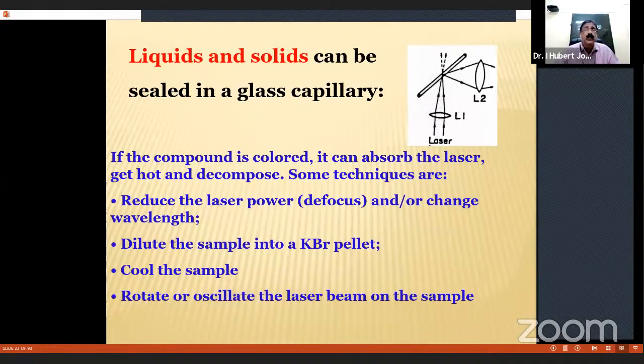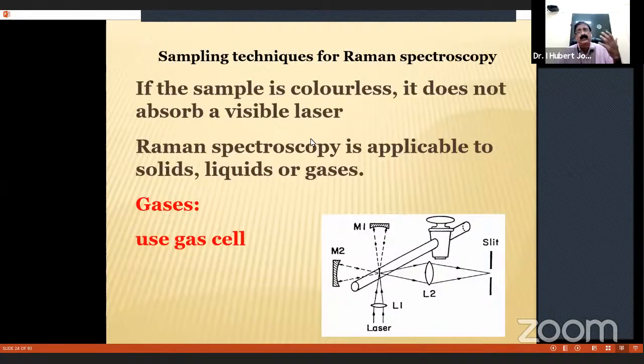In the case of a liquid sample or gas, or solids such as powder, the molecular sample can be sealed in a glass tube. Suppose the sample is hygroscopic: you can evacuate the sample and seal it, then record the Raman spectra. If it is a gas, just fill the gas in the tube, replace the sample holder, and record the Raman spectra. So any kind of sample, either solid, liquid, or gas, you can record very quickly.